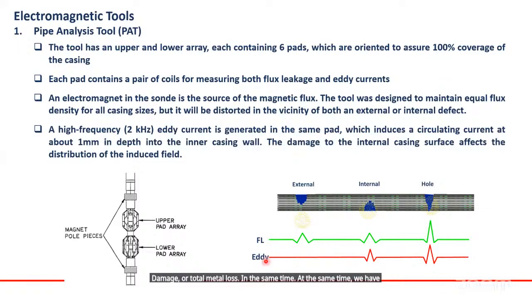At the same time, we have a source of eddy current that pushes a current 1 millimeter into the casing. If the inner diameter is good, the eddy current is good. If there is any damage in the inner diameter, it will distort the eddy current. So the flux gives you the total metal loss, and the eddy current gives you only the inner. If the total is not good and the inner is good, it means the corrosion is external. If the total is not good and the eddy current is not good, it means the corrosion is internal.